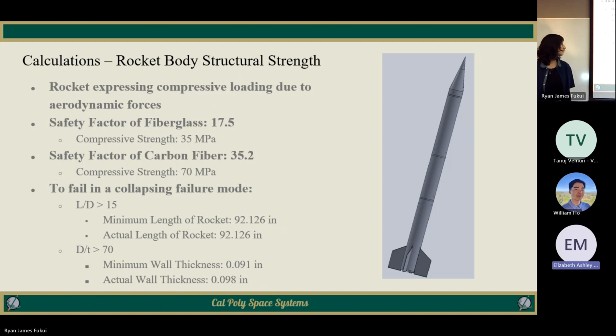Can you guys hear me okay, by the way? Yeah. Okay, cool. So first, to answer the question of why we have the wall thickness we do, you can see at the very bottom the diameter, it should be the other way. I'm sorry, I've been sick. My brain hasn't been working. It should be the diameter over the wall thickness should be less than 70. And if it was over 70, the tubes may fail at a compressive strength that's lower than the yield strength. And if so, it'd be failing in a buckling failure mode, and that's not what we want because that could be a sudden failure. We want it in the collapsing. So that's the reason that we need that minimum wall thickness.